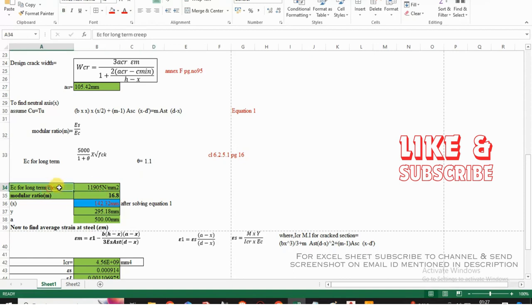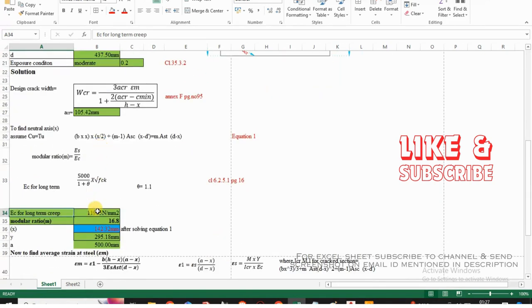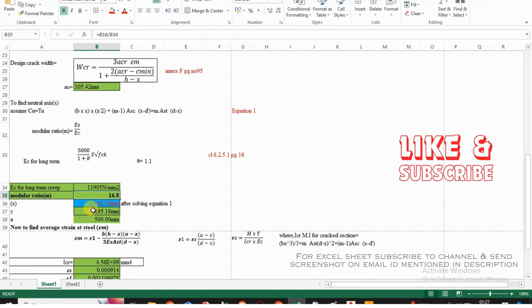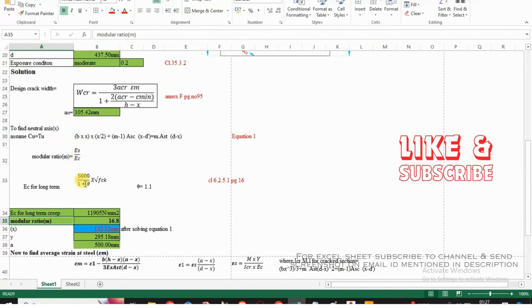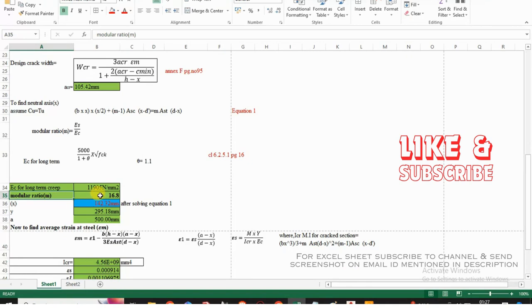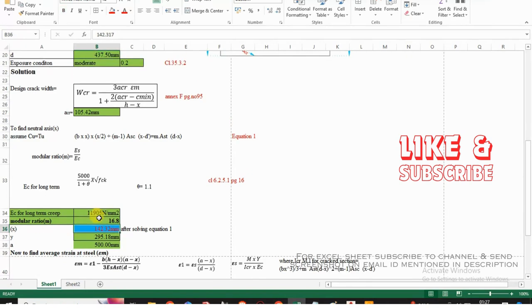So for long term creep, when we substitute 5000 divided by 1 plus 1.1 into under root fck, that is 25, we'll get the long term modulus 11905 newton per mm square. So modular ratio is equal to 2 into 10 to power 5 divided by 11905, we'll get 16.8. Having calculated 16.8, that is modular ratio, substitute this value in this equation and you will find the value of x, that is neutral axis.